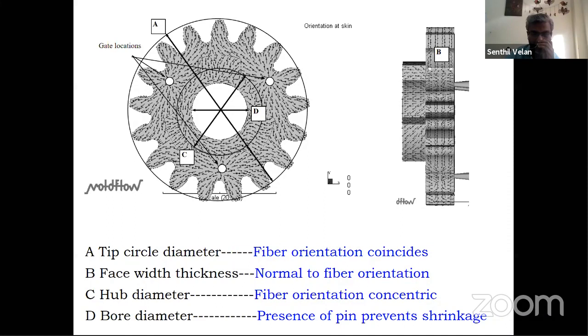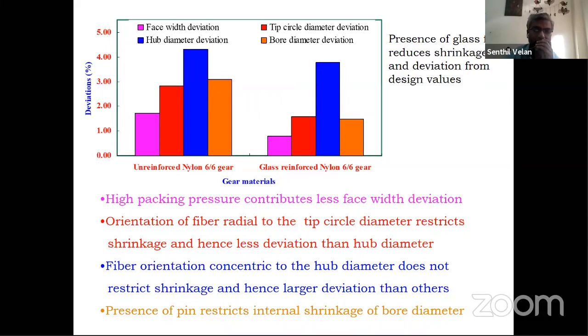In addition, the bore diameter pin is going to prevent the shrinkage. This is an internal core-like material. Typically, if you look at this, that was the predicted one, and this is the actual measurement. In the actual measurement, if you look at the hub diameter and face width, you will see the difference. This is for one class of material, the unreinforced material. The deviation is very large over here, whereas the face width deviation is very, very small. When you add the fiber, exactly the same behavior but slightly lower. The deviation from the actual measurement is slightly reduced because of the presence of the fiber.